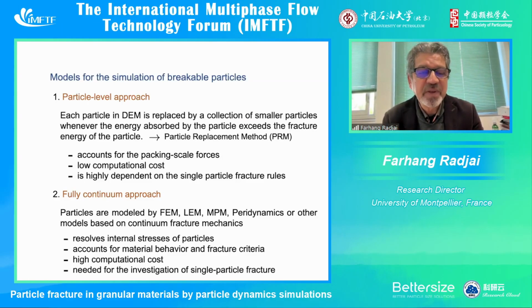For models of simulations of breakable particles, we can say we have at least four methods. At the particle level, we can use DEM, discrete element method. And using them, we also have different methods, such as particle replacement methods, where when a particle breaks, we replace it by smaller particles. This is a very fast approach, in the sense that when we replace the broken particle by several smaller fragments, we just have to figure out which particles should replace the parent particle. It has a low computational cost because we're really not modeling what is happening during particle breakage. But it is, of course, highly dependent on the physics of particle fracture rules that we use for breakage.